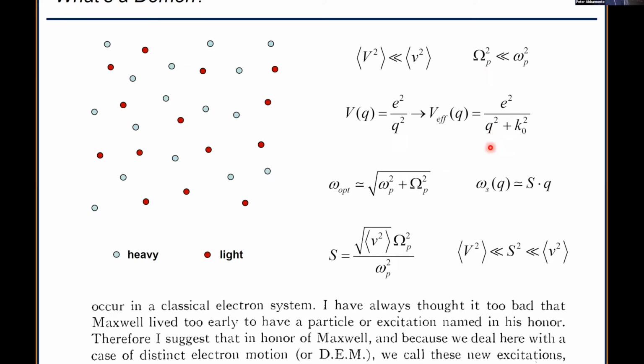And what happens is you get 2 modes. One of them sits up at the sum of the 2 frequencies, and the other one ends up sitting at low frequency, and this really isn't moving fast, but it ends up being gapless, and it has a velocity s that's actually bounded by the Fermi velocities of the 2 different species of carriers. So it's not a rigorous numerical calculation. It was sort of a heuristic argument, but he argued that any material where you have more than one species of charge carrier, such an excitation could exist.